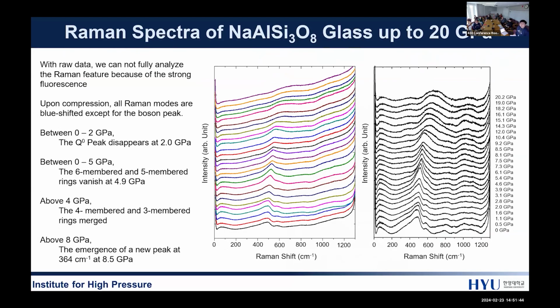This is my Raman measurement of albite. Due to the strong fluorescence, it is hard to analyze the raw data of albite, so I removed the background. During the compression, except for the boson peak below 200 inverse centimeter, all Raman modes are blue shifted.